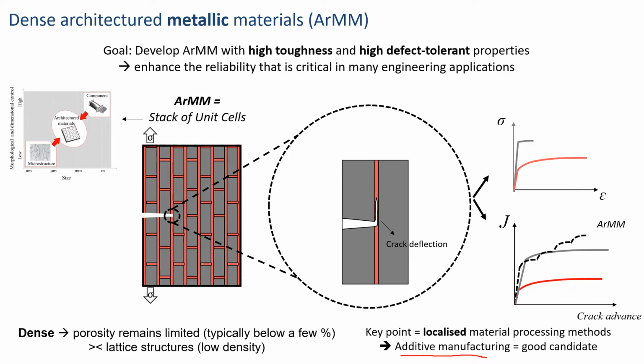So what we want to do is being able to introduce, for example, interfaces within the materials, and these interfaces have a low yield stress but a high ductility. And at the same time, we want to be able to generate cells in between these interfaces which have a high yield stress but which would be typically associated with a lower ductility. And by combining these two phases, or you can see it as materials, we will probably be able to introduce toughening mechanisms within the material, such as crack deflection, for example.